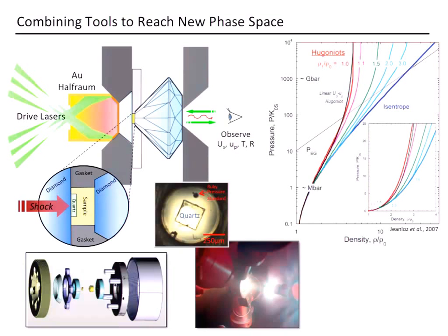That initial density, the rho naught in the Hugoniot equations, is important. Being able to tune the initial density means we can tune the phase space we end up in. What I'm showing here is the final compressed density over the initial density, and you can see that as we increase the initial density, we can access the space between the Hugoniot and the isentrope in pressure-density or pressure-temperature space. This is a really nice method to fine-tune where you're going to end up with your shock, instead of just landing on that principal Hugoniot, the blue curve I showed you earlier in the talk.